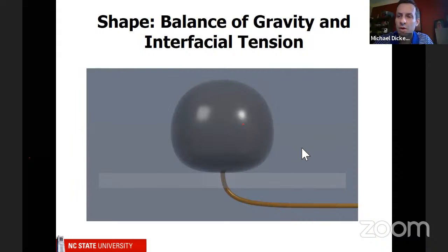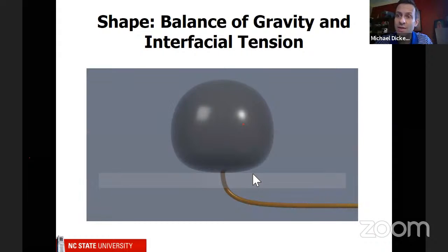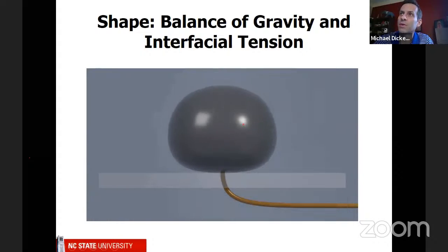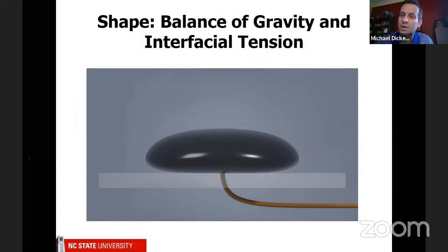So this shows you our experiment. We've got a metal wire, a very small metal wire that contacts the liquid metal. It's sitting on a surface, and we're doing this in sodium hydroxide, so there's no oxide layer, at least not initially. And when we apply the voltage, the droplet is going to squish down, and depending on that height, we can figure out the surface tension.